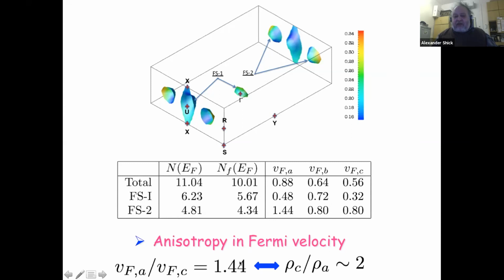Moreover, we can calculate the Fermi velocity, and we see that there is a pronounced anisotropy in the Fermi velocity. If you take the ratio of the Fermi velocity, say, along the A direction and the C direction, it is about 1.44. Naively, if the electron moves faster, then the material conducts better. It means that this ratio, at least qualitatively, is inversely proportional to the ratio of the resistivity. And actually, the experimental ratio is about 2.